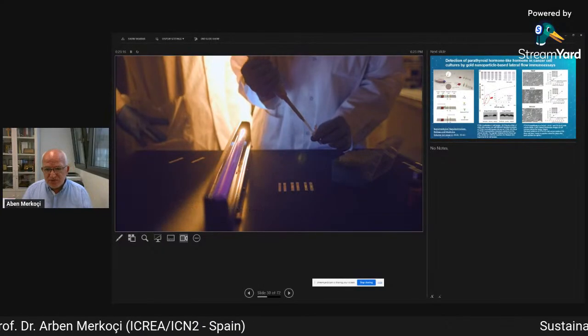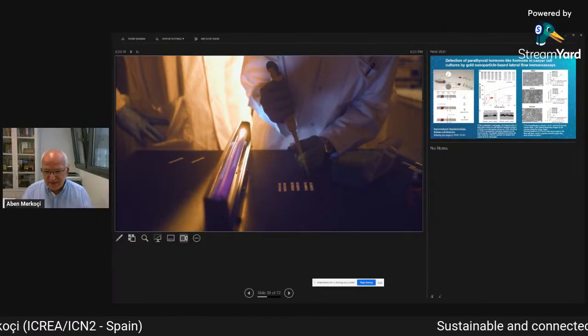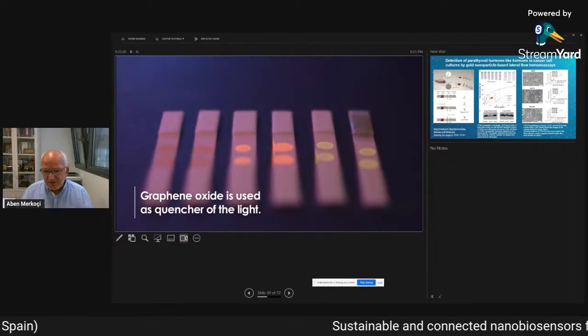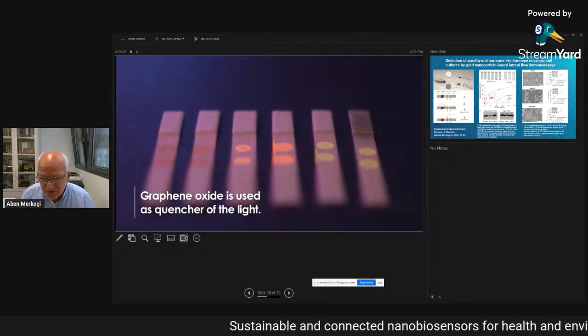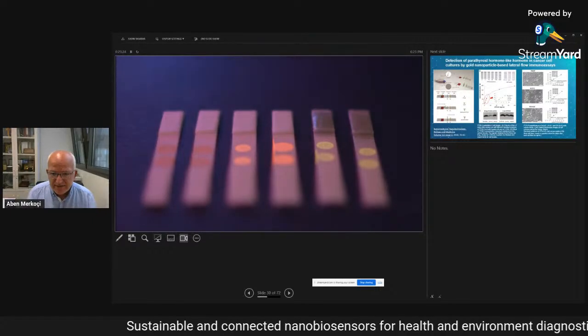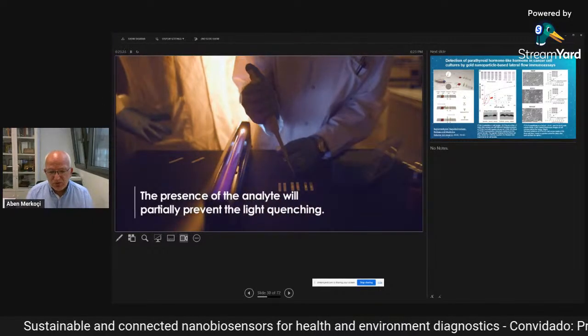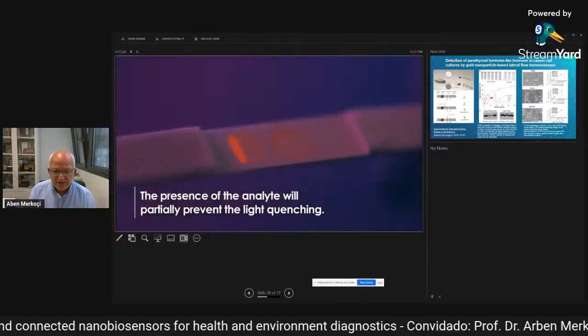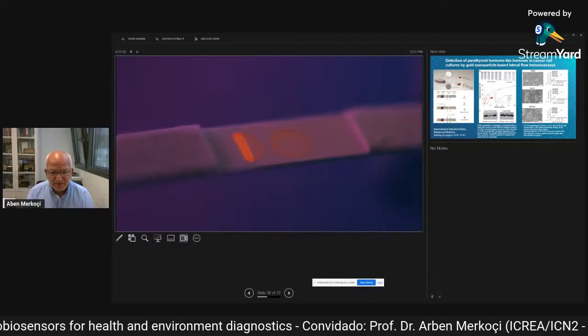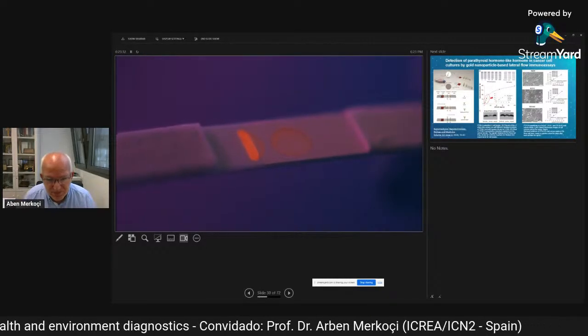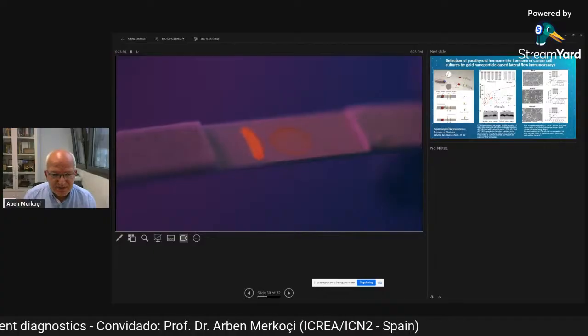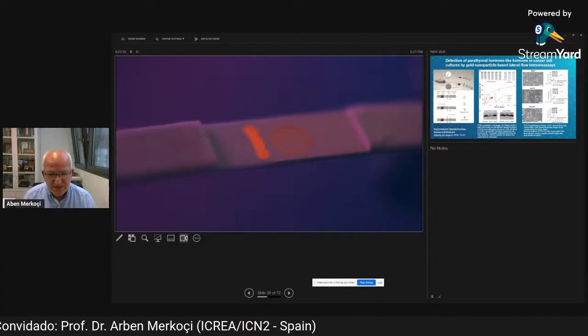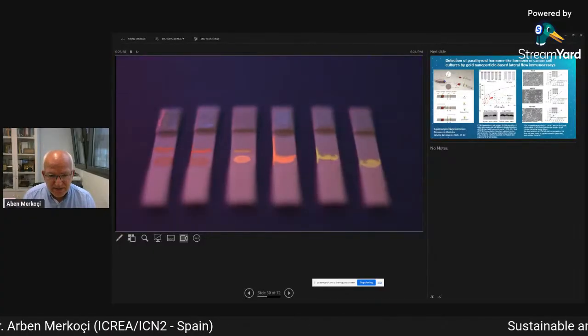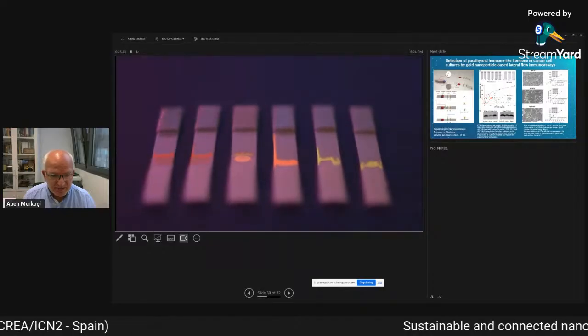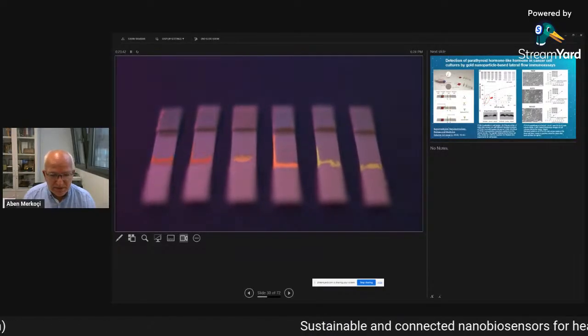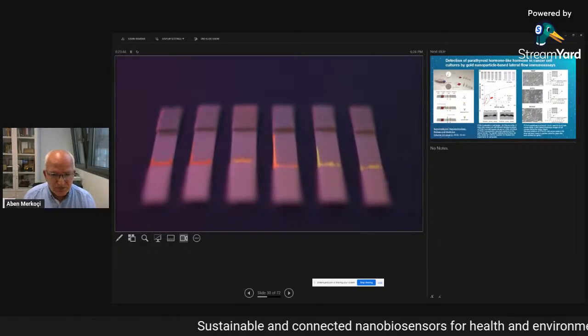Afterwards, we use the graphene oxide suspension, and due to the interaction of graphene oxide with these quantum dots, the light is quenched. So we follow this quenching of the light and correlate this quenching of the light with the presence, absence of the bacteria. So this is really very simple. You can imagine that if you change the receptor, you can detect any kind of bacteria. You can also do multi-detection based on what you want to do.